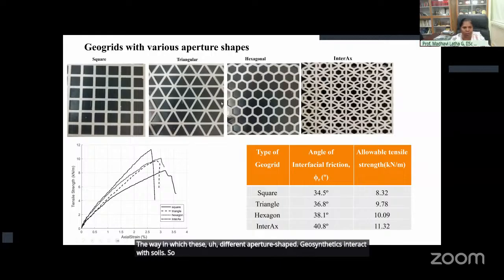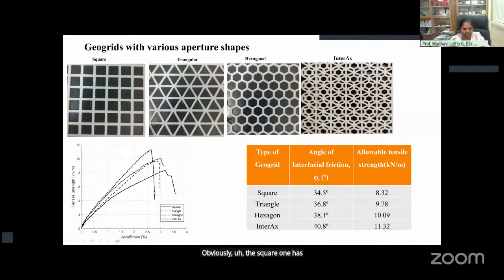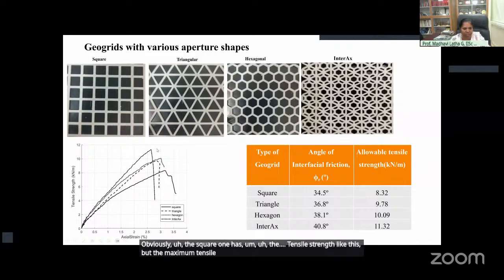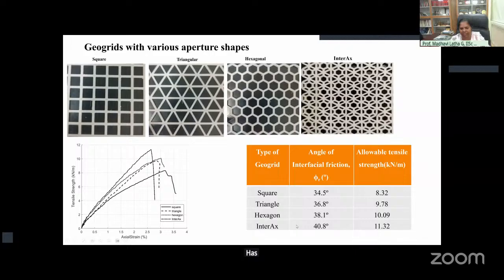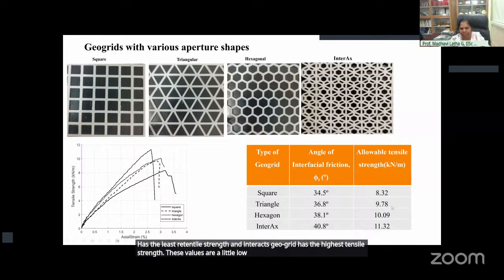So when we try to print these with the same aperture area but different aperture shapes, what we realized is, when we compare the tensile strength of these materials, obviously the square one has the tensile strength like this, but the maximum tensile strength is reported by the Interax geogrid. There's also a table which tells you that the square geogrid has the least tensile strength and Interax geogrid has the highest tensile strength. These values are a little low here, mainly because we used PLA, which is a low strength polymer.